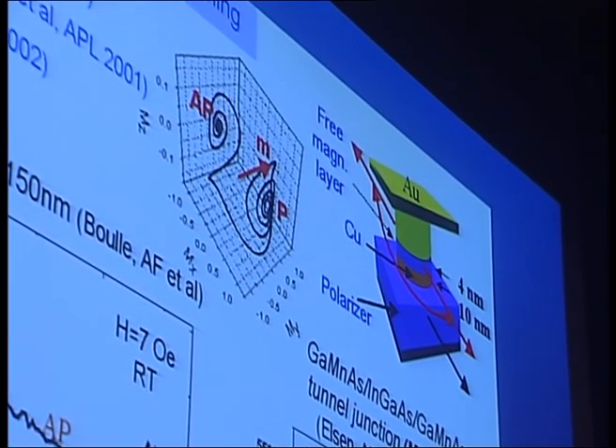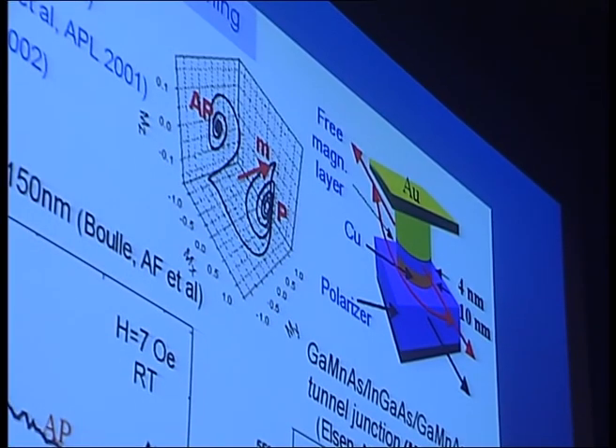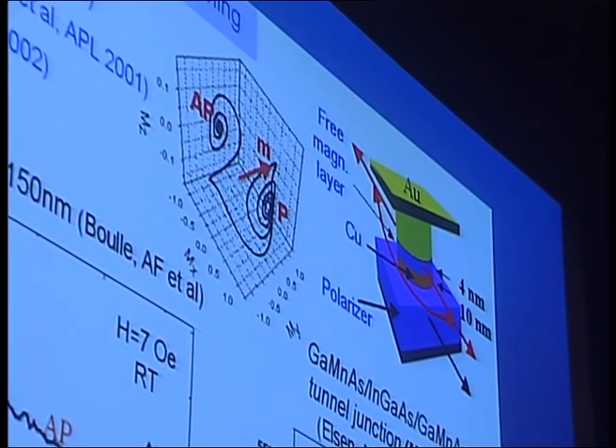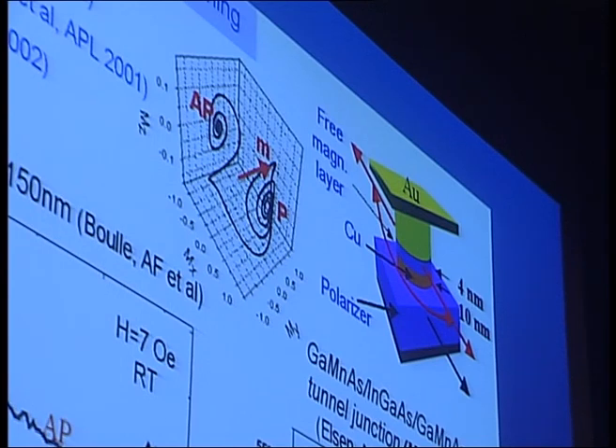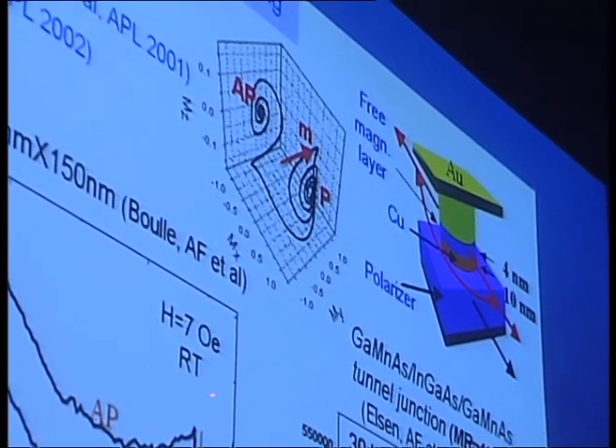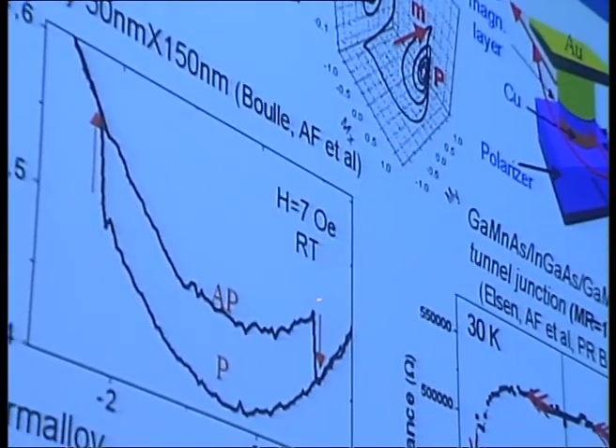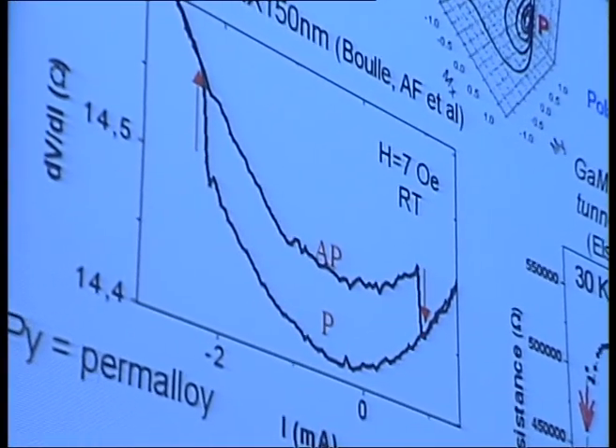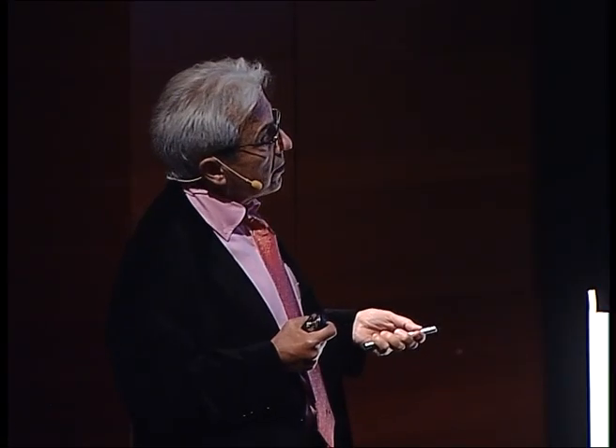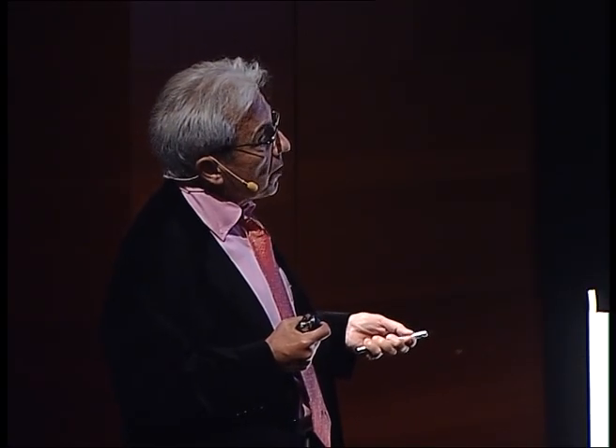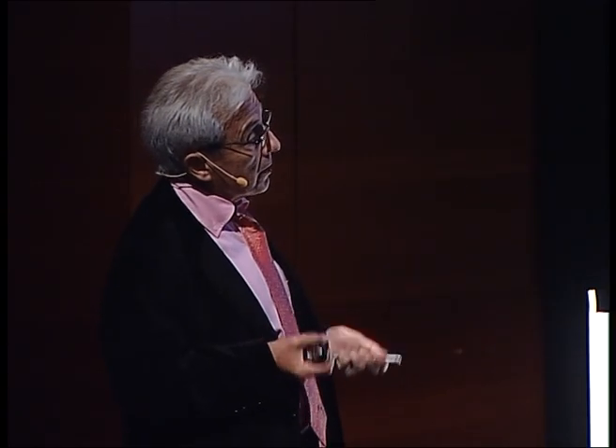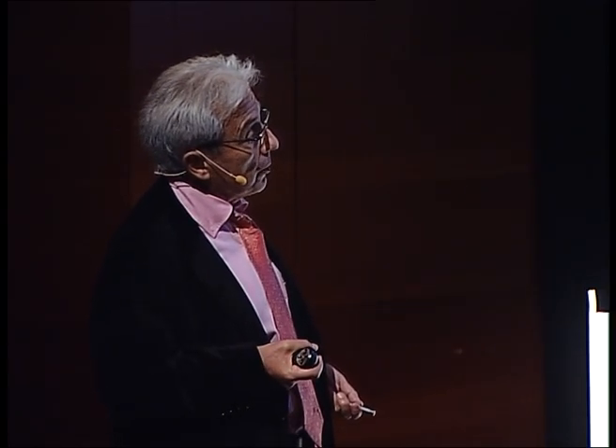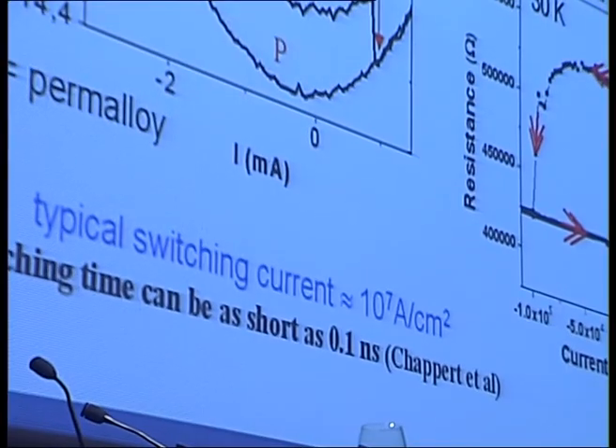You can see on this figure, for example, as a function of the current, the increase of the resistance, revealing the switching from parallel to anti-parallel. And by reversing the current, you can now switch the system from anti-parallel to parallel. The current densities are relatively high, but what is interesting for application is that the switching time can be very short, 1/10 of a nanosecond, and this is very interesting, for example, for the switching of the new generation of MRAMs.